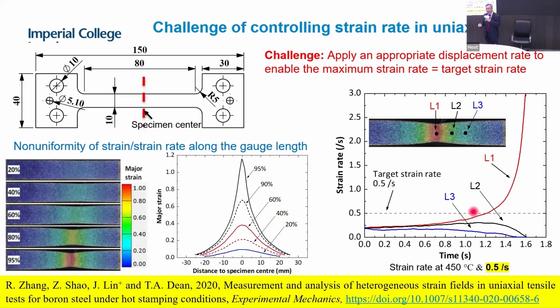If we look at the strain rates, for example, at this L1 location, the strain rate increases like this. If you look at L3, the strain rate is like this. At high temperatures, we know the strain rate is very important to get accurate data. And our challenge is how to apply the proper displacement so that the maximum strain rate within the specimen equals the target strain rate. The target strain rate, for example, we put 0.5, which is very difficult to achieve using the traditional method.